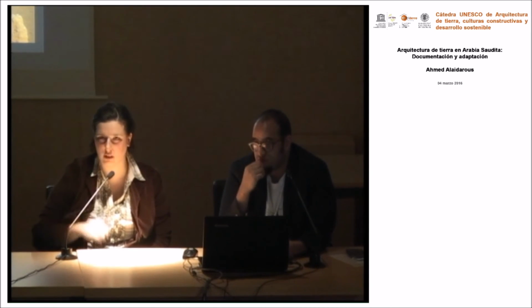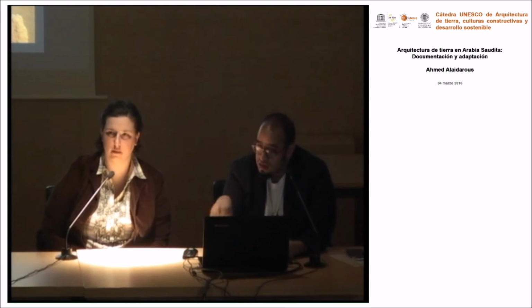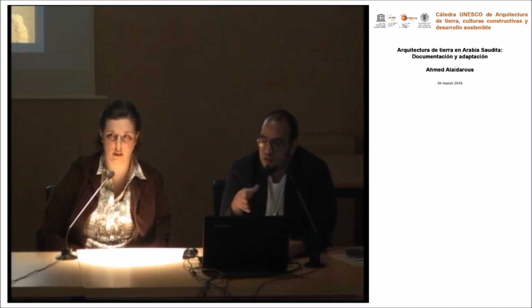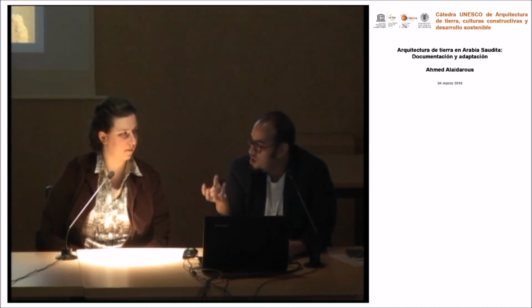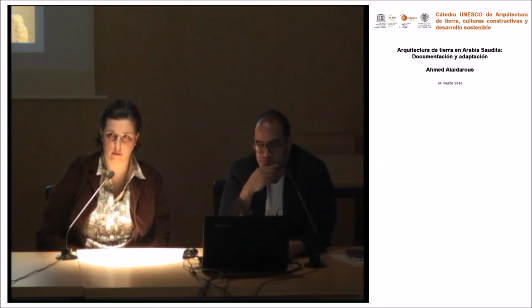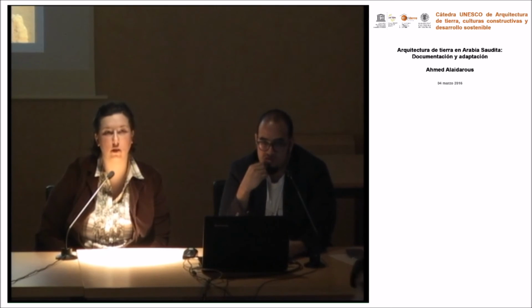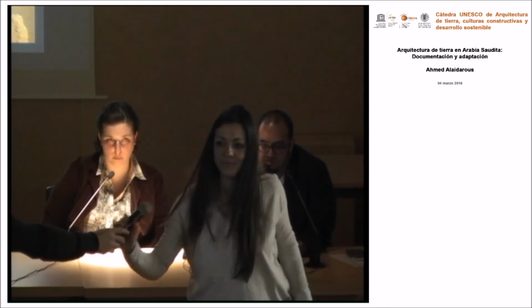Adding water bit by bit while they mix it. And during 2 weeks or a month, when it becomes dry, they just wait. Cement, between 5 and 6%. I think I said 10 before, but it is 6.